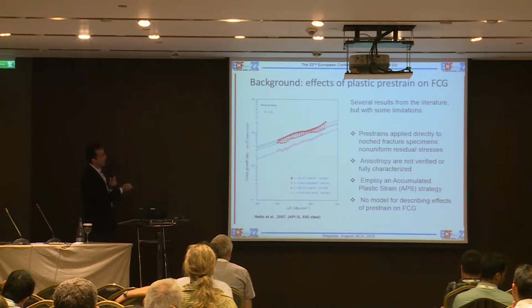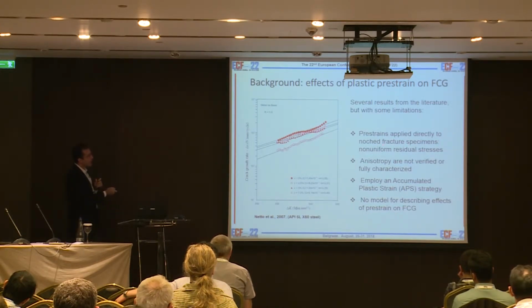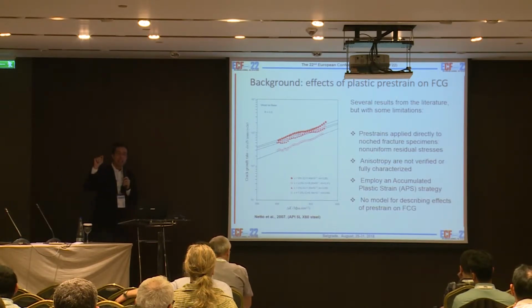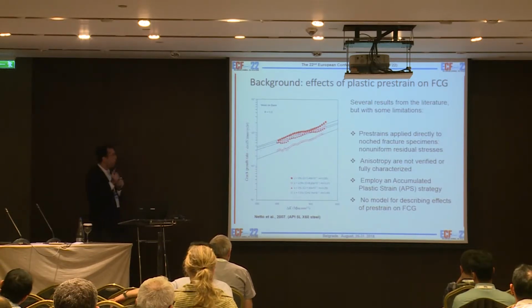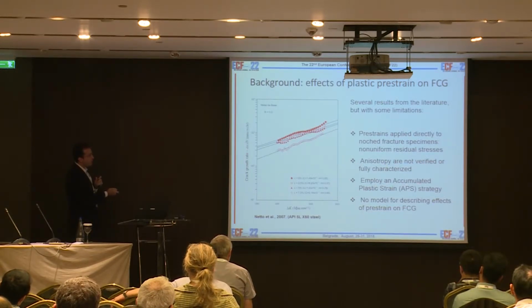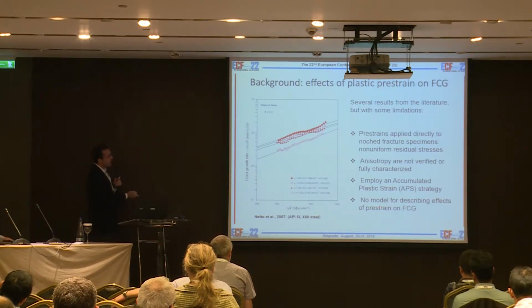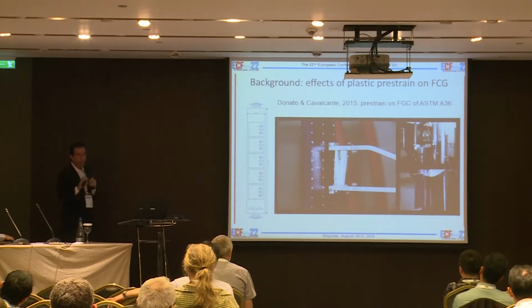Most papers apply the prestrain directly to CT specimens. So the stress distributions are not uniform. So you have non-uniform residual stresses in every position that the fatigue crack growth will progress. Anisotropy is not considered. They use the concept of accumulated plastic strain. It's not wrong, but we didn't want to use it. And they use no model to describe the fatigue crack growth effects in terms of the material response. So we developed a different technique.